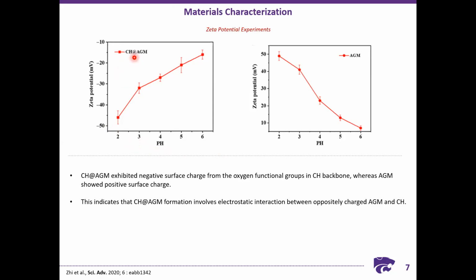As you can see, for the CH coated on AGM, the zeta potential values are negative, indicating a negative surface charge. This negative surface charge comes from the oxygen functional groups present in the CH backbone, while the AGM has a positive surface charge. So this also confirms that CH has been coated on top of AGM. It also gives insight into the preparation of CH at AGM. Since AGM and collagen hydrolysate are oppositely charged, when they dip the AGM separator in the 5-8% CH solution, the CH molecules self-assemble because of the electrostatic interaction.